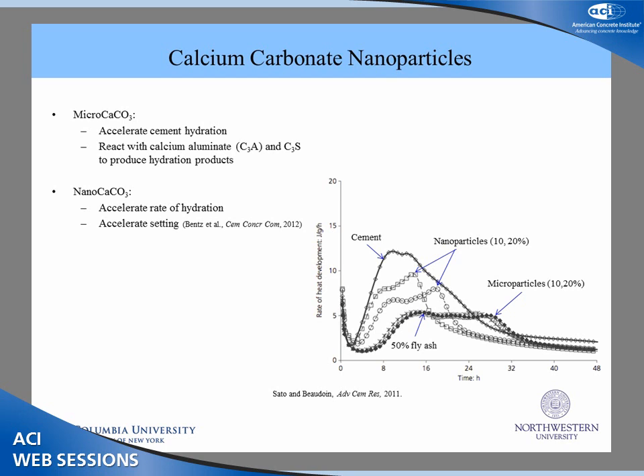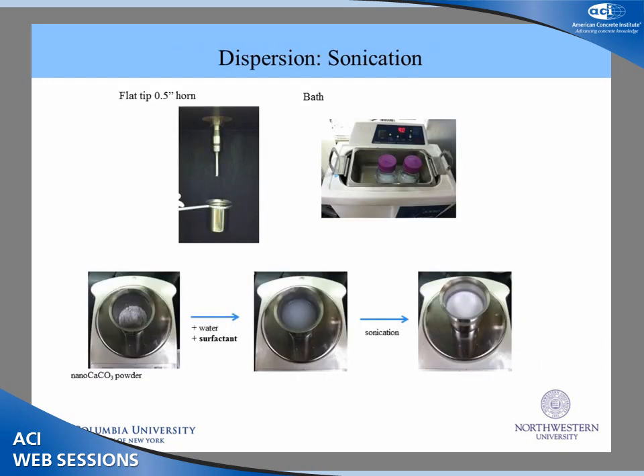But if you look at the addition level, 10 and 20% is rather high for nanomaterials. So in our work, what we tried to explore is, is it possible to still exhibit these enhanced effects with nanocalcium carbonate, but at lower addition levels? And can that be achieved through more effective dispersion? So we attempted dispersion through sonication. This is very well accepted to be an effective method of dispersing nanoparticles, and it's a mechanical method. And we compared Horn sonication versus bath sonication. They each introduced their own advantages. With Horn sonication, it's a more energy-intensive method, so it's more effective. But with bath sonication, you can scale, so you can sonicate more material. And in construction, that's obviously very important.